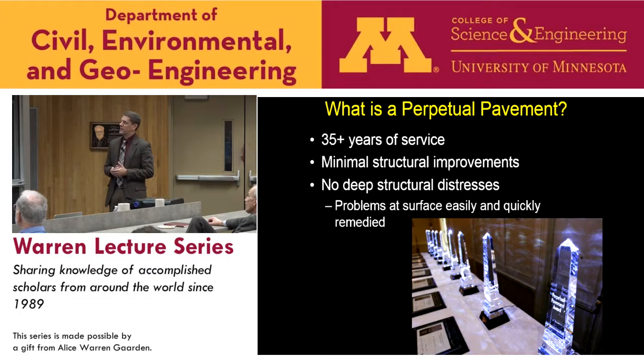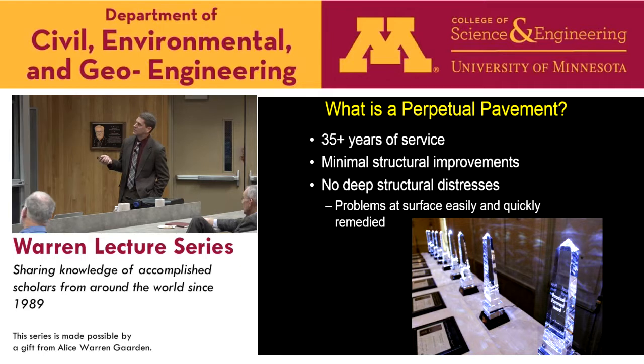So for perpetual pavement, there's actually an award program, and Minnesota leads the country in winning these perpetual pavement awards. The Minnesota Asphalt Pavement Association has been very active in promoting this concept, and Jill Thomas, another graduate of this program, is the director of MAPA, and I think every year there's been an award, Minnesota's gotten one, going back to 2000. So you all lead the country in these awards. And the definition is that they have at least 35 years of service. Many of them have 50 or more years of service. Minimal structural improvement, so it's not like we built the pavement and then added 6 inches. There's a 2-inch overlay per time with a certain interval between overlays. So minimal structural improvements, and then no deep structural distresses.